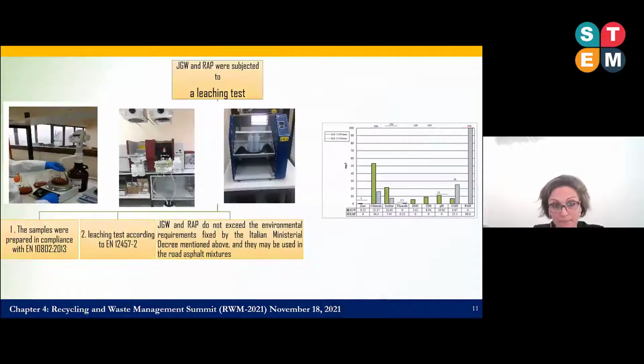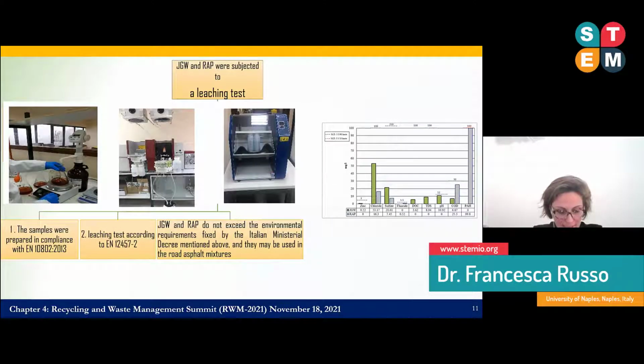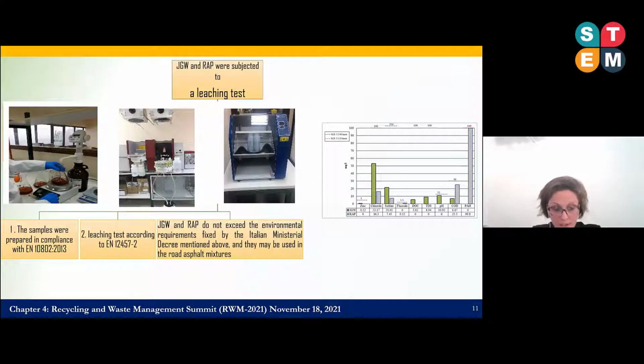Jet grouting waste and reclaimed asphalt pavement were subjected to a leaching test. We don't have the equipment in the road laboratory to carry out these tests, and so the procedure was carried out by a certified chemical laboratory. 2 main steps can be mentioned. The samples were prepared in compliance with an international standard, and the leaching test was conducted at 20 plus or minus 5 degrees. Results, as you can see on the right side of the figure, emphasize how jet grouting waste, in green bars in the graph, and RAP, in the gray bars, don't exceed the environmental requirements fixed by the Italian ministerial decree, and they may be used as aggregate in road bituminous mixtures.